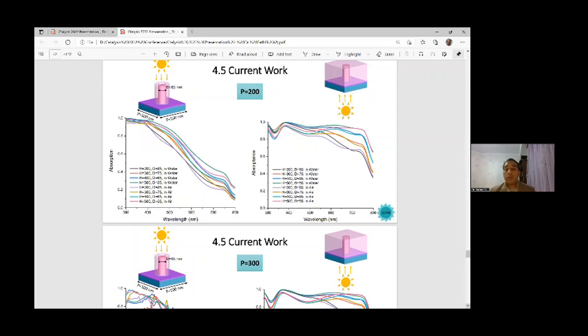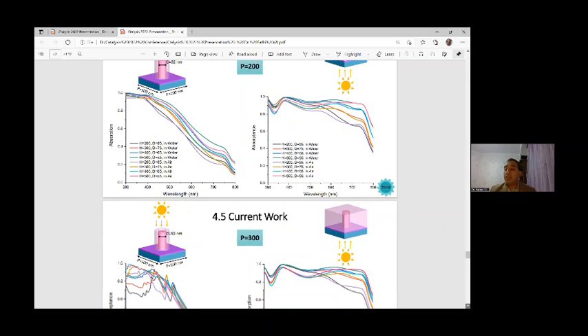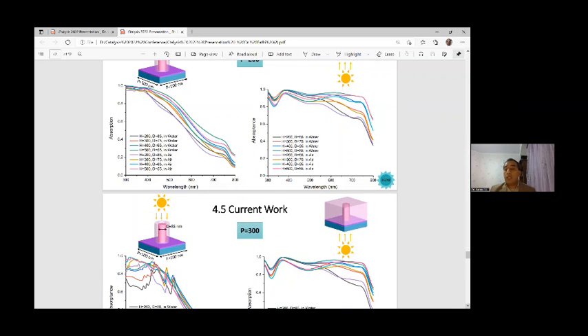For structure 2, as you can see and compare, we have the best case for P equal to 200 nanometers because of light trapping. We have trapping of light, and as a result, the absorption increases. The enhancement of performance here is due to the trapping of light, and so the absorption is enhanced.